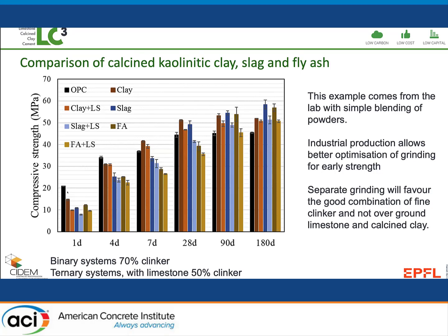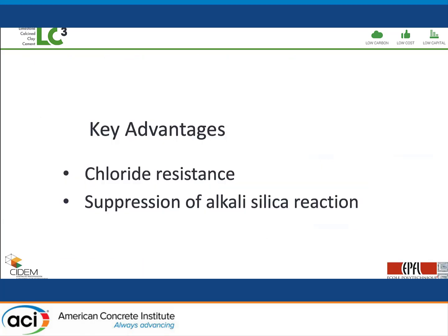And here, when we're blending in the lab, we do have lower strengths at 1 day, but again, in an industrial context where you can adjust your particle size distribution, you can maybe use separate grinding for the clinker part and then the calcined clay and the limestone part. We have several examples from real life situations where we can get the same strength even at 1 day.